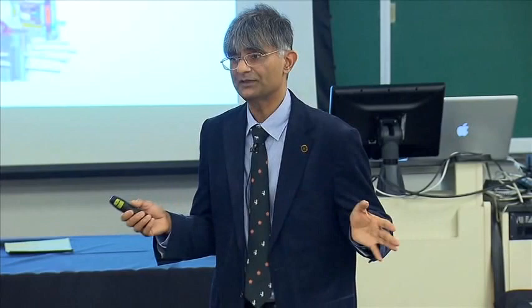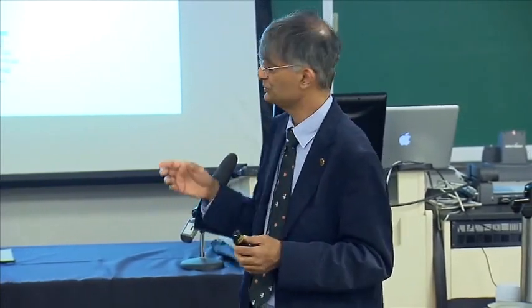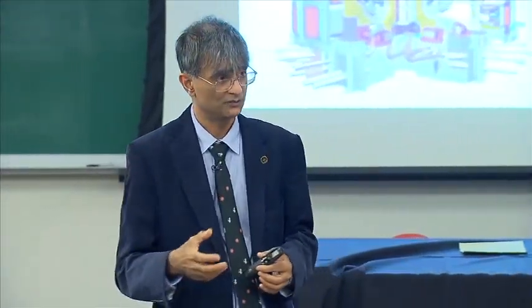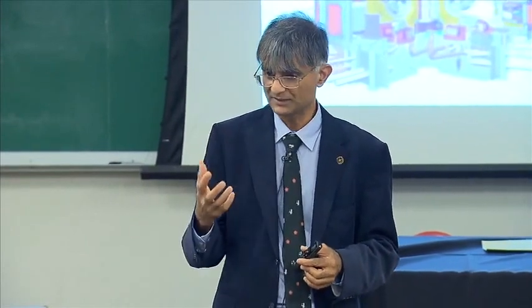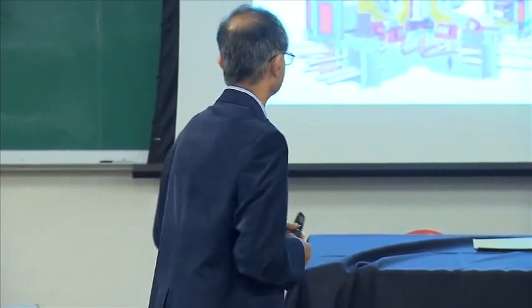Okay? But we do not have any knowledge about materials behaving under these circumstances, and there is no experimental facility in which you can expose the material to 200 dPa of damage. And yet, you know, we are going to spend several billion pounds in making this reactor. Okay? So how do you cope with that? In this case, you have absolutely no choice except to do some kind of modeling. Yeah? And you do modeling on the basis of the data that you have, which is from the fission program, where the dPa at most goes up to something like 30 displacements per atom.